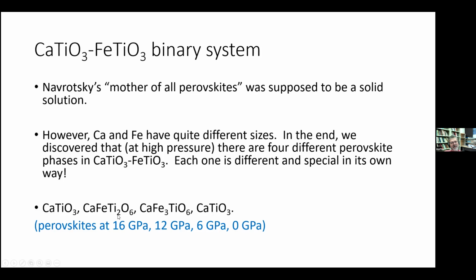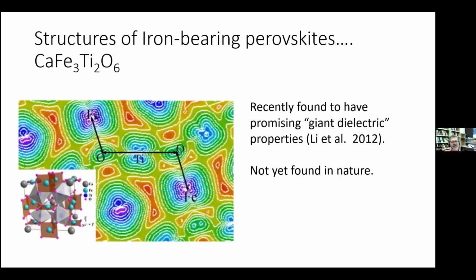It was calcium iron titanate with this stoichiometry, with 1-to-1 calcium to iron, and then one with 3-to-1 iron to calcium. And the iron in this one is in square planar coordination, which is quite surprising. But there are 4 other oxygens not that far away. So it's really kind of a coordinated. Oh, sorry, that's a little fuzzy.